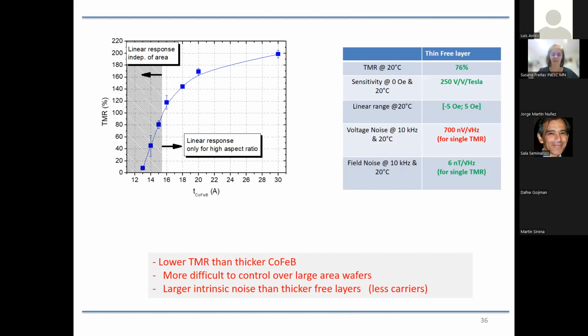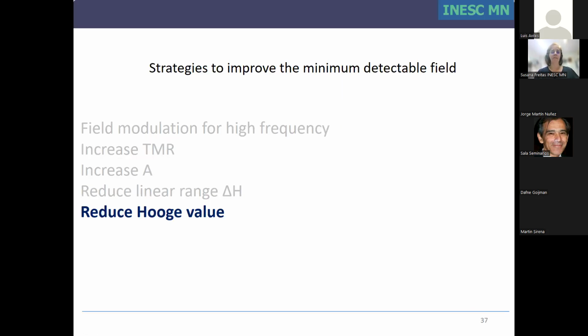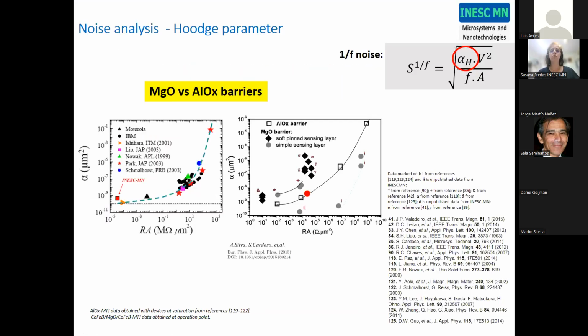So at the end, it's a trade-off between these two effects, and we need to recalculate if the gain in signal to noise ratio is worthwhile when we look at the TMR drop that we have if we reduce the thickness. So finally, going to the Hooge value. The Hooge value is a parameter that appears just as a phenomenological number that helps to fit the noise spectrum. And here there is a lot of work done in the past years, very systematic, comparing different barriers, different values from companies and from everywhere, and people use this as the factor that nobody can control, because we don't know exactly where the Hooge parameter comes from. We know that it's there, and if we fit, this is the free parameter that we gain.